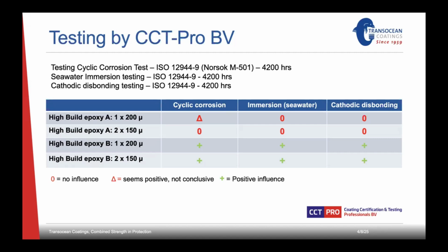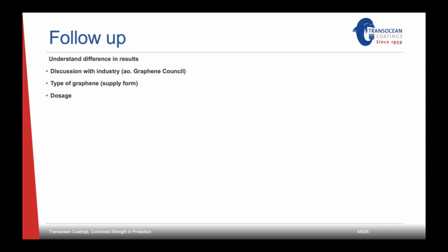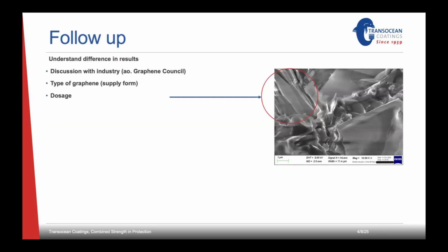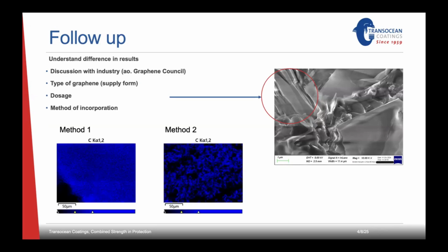Because of the good results we had, we already started doing test applications in practice in collaboration with Kossan Paint. But we also tried to understand why we see a difference in the results. So we discussed with the industry, amongst others Terrance from the Graphene Council. We thought the dosage form of graphene may have an influence, but also the dosage percentage itself. Sometimes you can use too much, and then the flakes are layered on top of each other, and you do not get that nice laminar effect, which gives the good barrier against water penetration. So that made us think the dose is maybe also important. Someone also said to me, if it doesn't work, use less.